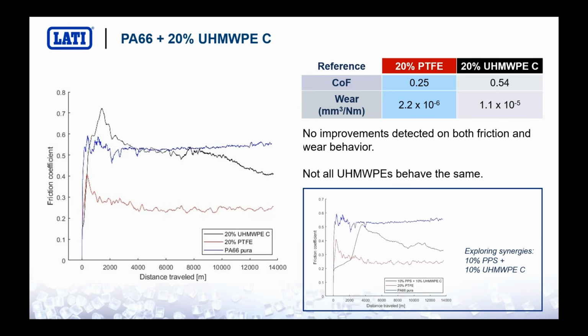So the fact that taking advantage from both PPS and ultra-high molecular weight polyethylene C-type, we obtain better results than the use of the single additives. So in this case, the synergic effect was confirmed by the friction coefficient, which was very low compared to the two materials, one with only PPS and the other with ultra-high molecular weight polyethylene only.